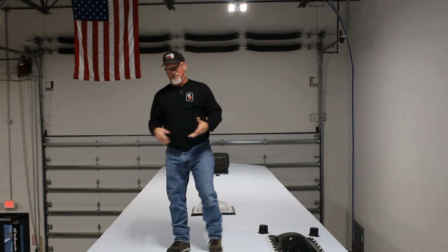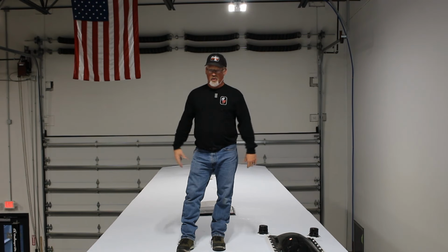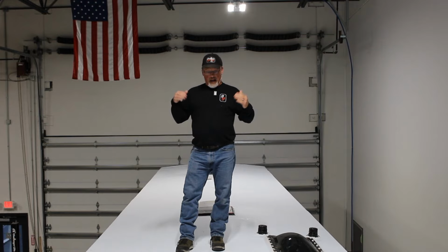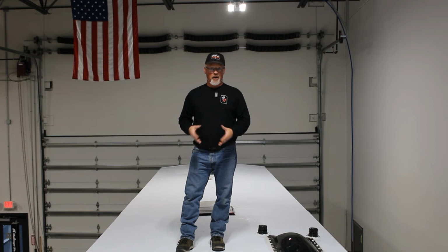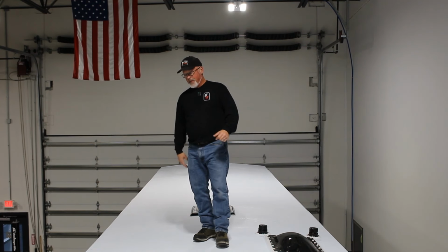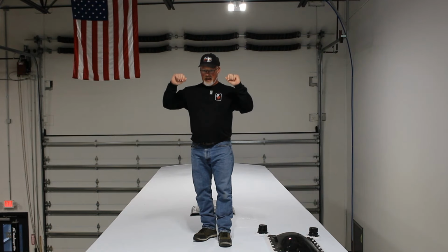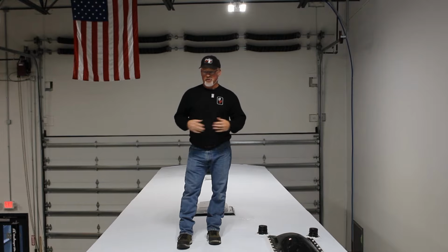The reason we're using aliphatic over a pure polyurea with a top coat is once this roof is sprayed, the color change is going to be very, very minimal over a long, long period of time. I want to use the highest end product that requires the least amount of maintenance, and this is the product to use. If we use a pure poly, like a lot of the competition does, we're going to have to top coat that, and over time that top coat will give itself up. It'll come off, the UV will break it down, and it'll fall off, just like galvanizing or any of the other coatings. This is pure bright white aliphatic from the top of the roof all the way to the bottom of the coating. There's no top coats or anything else going on.